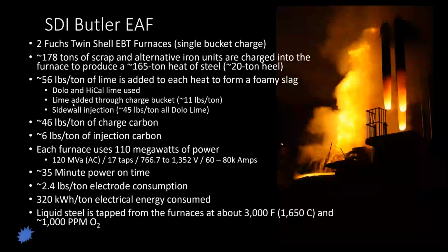A little bit about SDI specifically. We're running two Fuchs twin shell EBT electric arc furnaces. We're charging about 178 tons of scrap, and we're ending up with about a 165 ton heat. With a twin shell furnace, and being an AC shop, we run a relatively small heel compared to some people - only about a 20-ton heel. That's more of a thermodynamic problem than anything else.